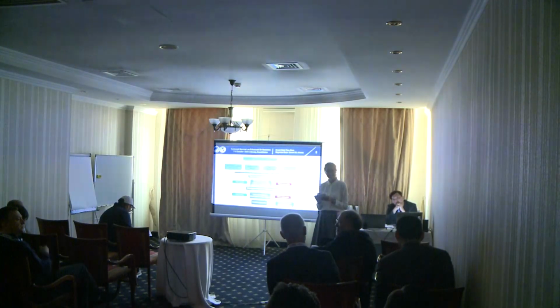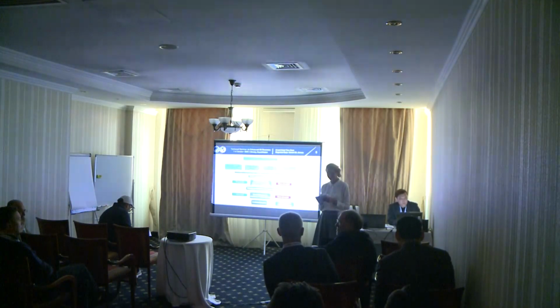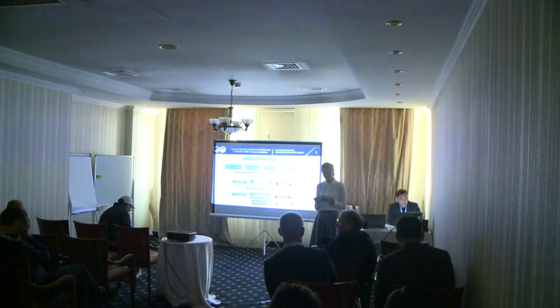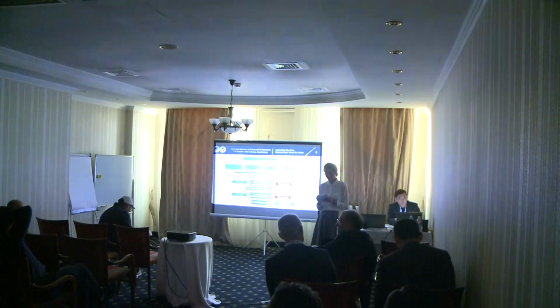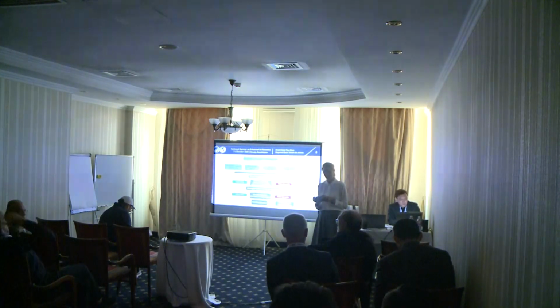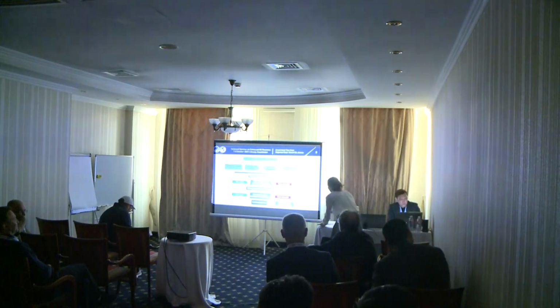These are changing, and the choice of even the filter diameter is important. But when we use a 3 or 5 micron filter, 47 millimeter, Nuclepore is perfect. Thank you for the valuable input.